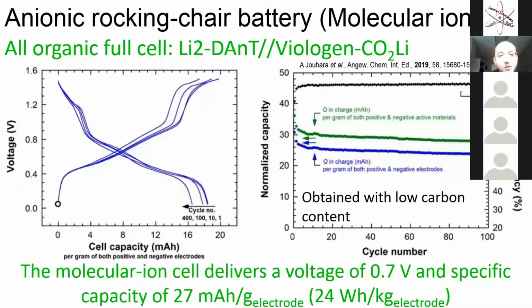And then if you combine this conjugated amine with the viologen in a full organic molecular ion, you will have this kind of curve with the voltage around 0.7 volt. You have a good reversibility, and you have a good, or I would say excellent cycling stability over 100 cycles. So this molecular ion still delivers a low voltage, 0.7, as well as a low specific capacity of 27 milliampere hour per gram. And here the energy density is very low, 24. But the concept is good.